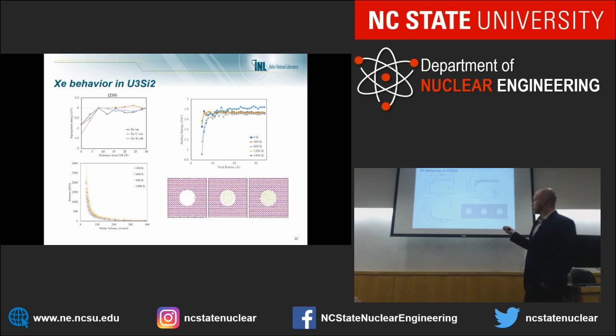So what we're doing is we're adding in more and more xenon into these systems to increase the pressure inside the bubble. We can get a pressure as a function of the molar volume for the xenon in these systems, and then we can fit an equation of state to this information.